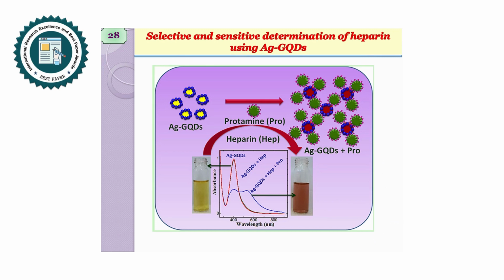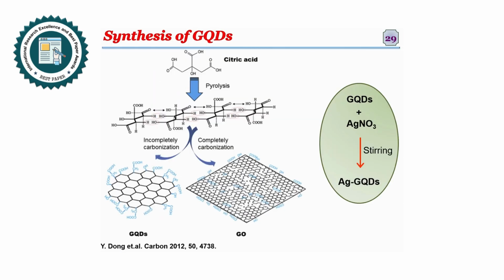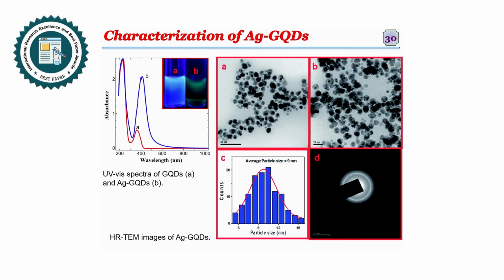So the second case is silver GQDs. GQDs are another kind of carbon quantum dots, and here silver GQDs are formed, and they can be utilized for the determination of protamine. Initially GQDs are synthesized from the pyrolysis of citric acid. Incomplete carbonization leads to the GQDs, and complete carbonization leads to GO. This is according to the paper by Dong et al. in Carbon 2012. After the GQD formation, the GQDs are treated with silver nitrate by stirring, and there is a formation of silver GQDs. Here, the GQDs act as an autocatalyst to reduce silver nitrate to silver, and there is a formation of plenty of oxygen groups on the GQD surface, which leads to the fluorescence.